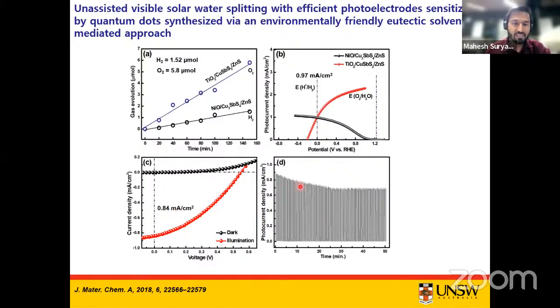Finally, we tested the stability and observed a similar trend: a decrement in the current density values after 1 hour of the stability test. That can again be correlated to the inability to sustain the harsh conditions of the aqueous electrolytes during light illumination. So far, I have explained improving the performance of TiO2 by sulfur doping or copper chalcogenide nanocrystal sensitization. Each time, we observed a decrement in the photocurrent density after a stability test of about 1 or 2 hours.